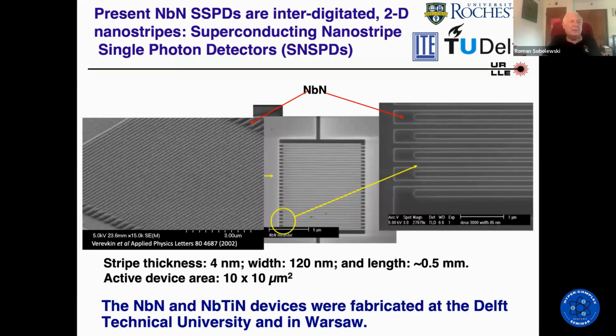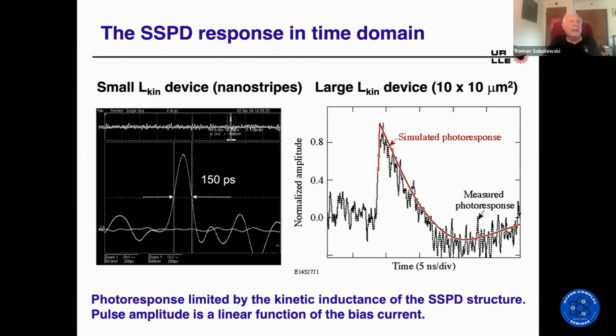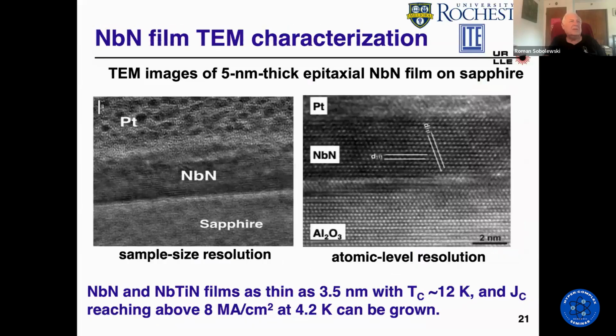Well, here you can see some experimental fabrication of large devices. And small devices would give us that ultra-fast photo response on the order of 100. The longer devices, because of kinetic inductance, since a huge meander contains a very large inductance, and resulting in that large resistive region, are typically on the order of a few nanoseconds photo response. Niobium nitride is deposited typically at high temperatures, and you can see a nice epitaxial growth on a sapphire substrate.